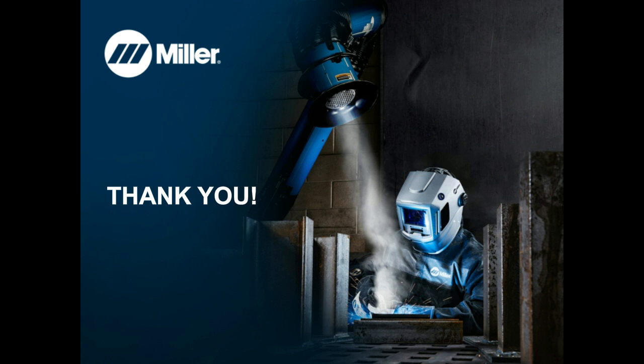This one now for Jeremy again. What's the minimum CFM for a portable fume extractor? That really depends on the size of the capture device. Typically what you're looking for is about 2,000 feet per minute to move weld fume inside the arm. So with our 8-inch arms, we do 1,200 CFM. 6-inch arms, we're around 600 CFM. So it really depends on the size of the arm, but you want to make sure you have a minimum, by ACGIH, of 2,000 feet per minute.